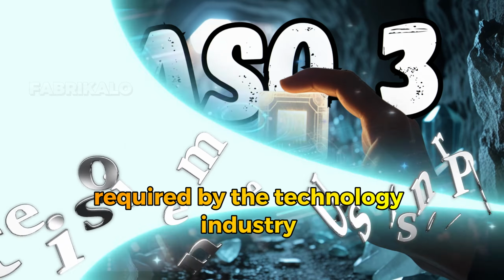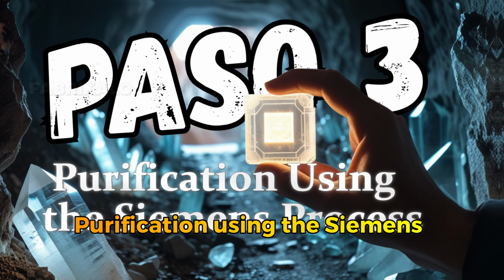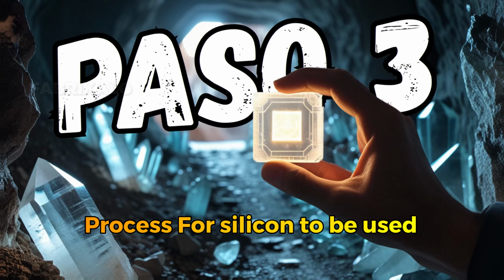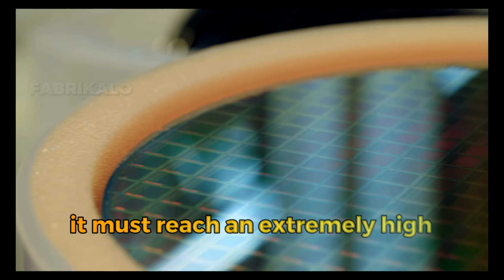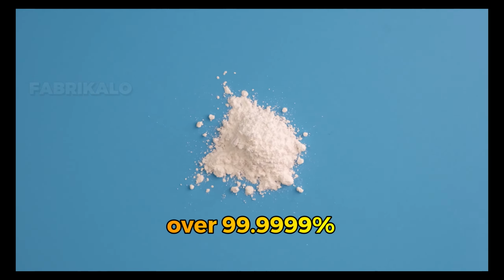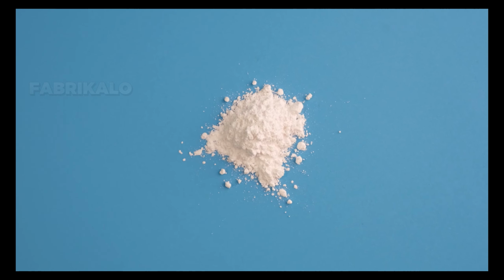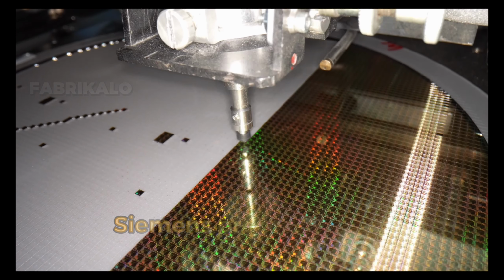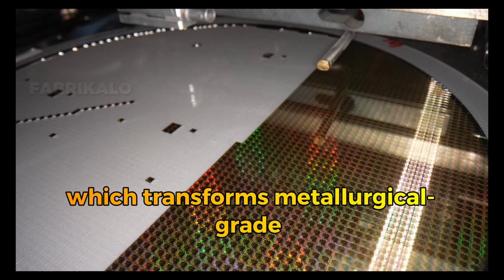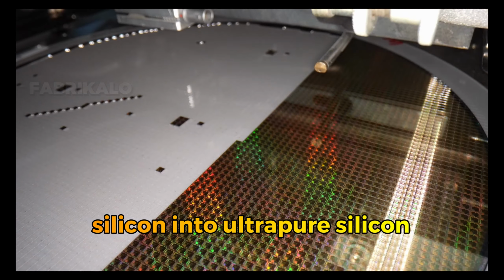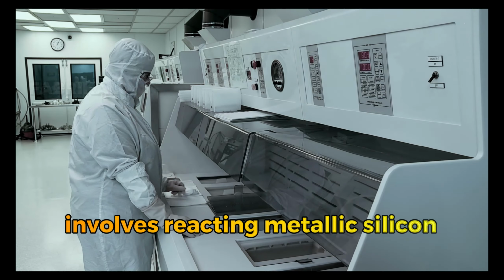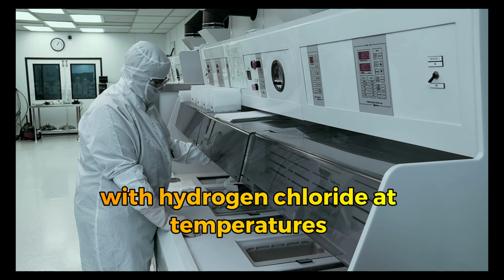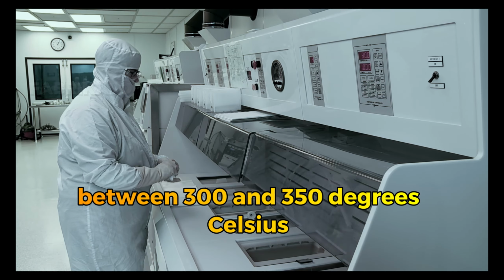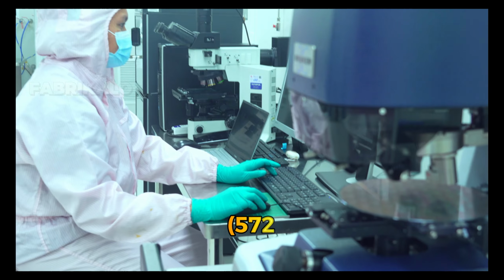technology industry. Step 3. Purification using the Siemens process. For silicon to be used in electronic and solar applications, it must reach an extremely high level of purity, over 99.9999%, known as electronic-grade silicon. To achieve this, an industrial method called the Siemens process is used, which transforms metallurgical-grade silicon into ultra-pure silicon. The first step of this process involves reacting metallic silicon with hydrogen chloride, HCl, at temperatures between 300 and 350 degrees Celsius, 572 to 662 degrees Fahrenheit.